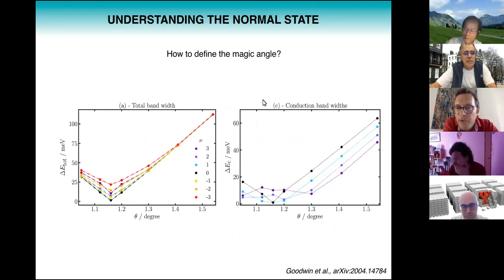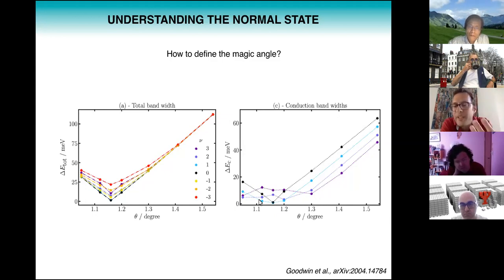So here I'm showing you now the width of the conduction bands of the electron doped system. And in contrast to the total bandwidth, which has this very nice V shape, you see that if I look at only the conduction bandwidth, I get a much more complicated picture, right? Here the different colors again describe different doping levels. So if I look at nu equals 3, you see my smallest bandwidth is actually at an angle of 1.3, and then it increases again. Similar for nu equals 2, I'm getting a couple of angles where I get very flat conduction bands. So this really asks the question, is the magic angle as identified from band structure theory really relevant to predict the twist angles where I should expect strong correlation phenomena? And I think the answer is probably not really.